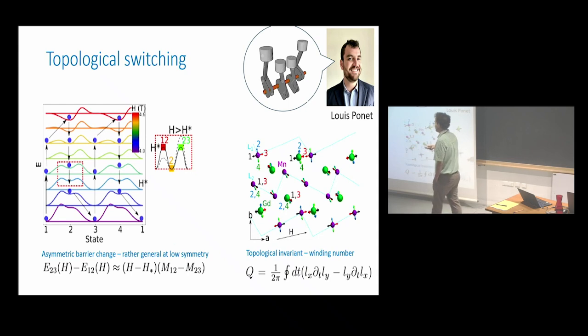So instead of the need to nucleate a new state in the minimum, this material gives a way to modify the potential energy surface in such a way that the state is guided around the loop not by domain nucleation, but in the bulk. At this point there is this spinodal decay. There is no way for this state to stay here. It will be forced to go to state 1, potentially in the bulk.